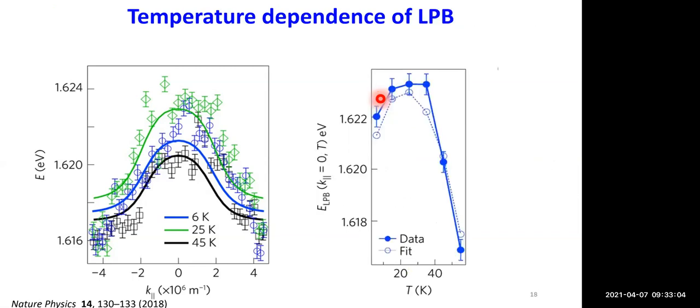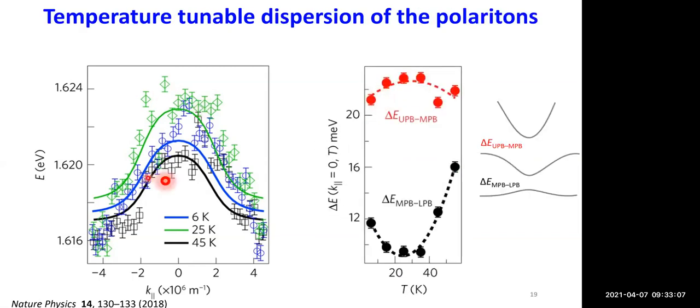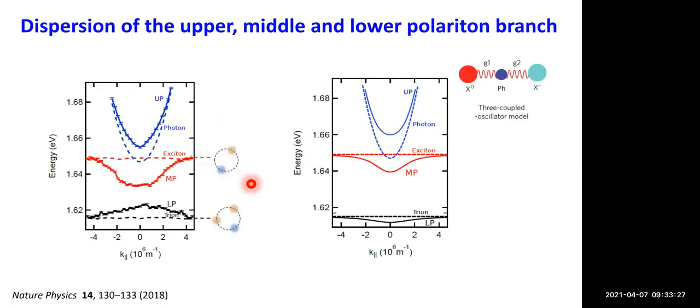Yeah, so basically this concavity that we see is dependent. From the calculations that we had, we could tell that this could be dependent on the doping level, because in earlier experiments where trion-polaritons were studied at a high concentration of trions, this effect was not seen. What they saw was a positive dispersion, similar to your coupled oscillator model. But here, our doping levels are fixed because we are not really engineering the doping. We are not tuning the doping. We have a fixed number of electrons, and that binds with the excitons to form trions.